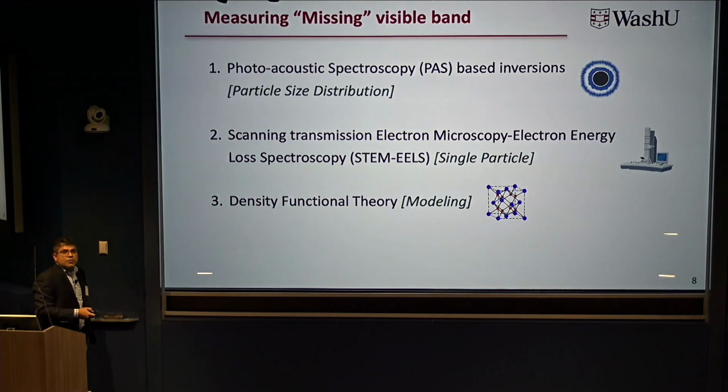So the approach we use is, on the particle scale, we use photoacoustic spectroscopy, essentially photons. Then with Rohan Mishra's expertise, we use scanning transmission electron microscopy coupled to EELS spectroscopy for single particles. And then we also use density functional theory to make sense of what we see. Density functional theory is essentially a quantum mechanical atomistic simulation model coupled to the non-equilibrium Green's function to give you pretty much the entire different material properties.